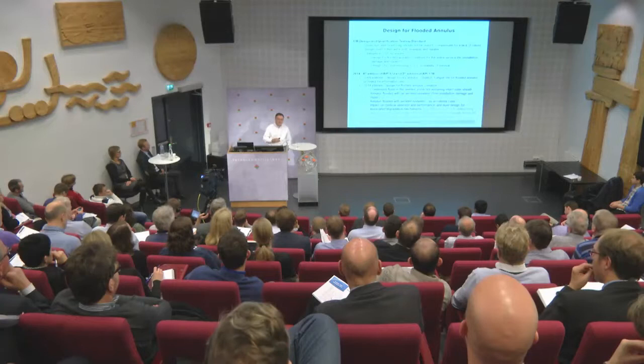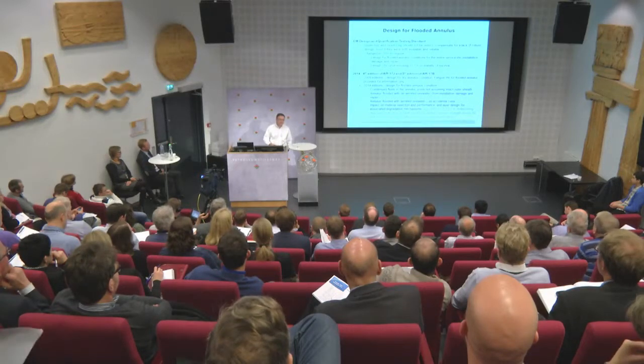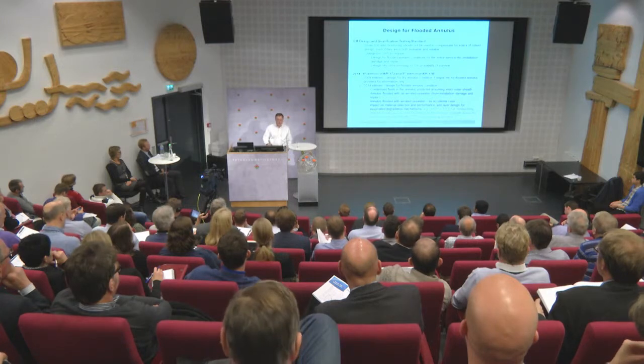That means that if you use the regular formula of mean minus 2 standard deviations to establish a design S-N curve, you're actually ensuring about 90% probability of survival. And we wanted to go with what we understood, which was 97.5%, as it comes from the steel riser world.